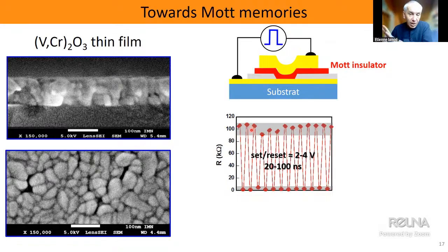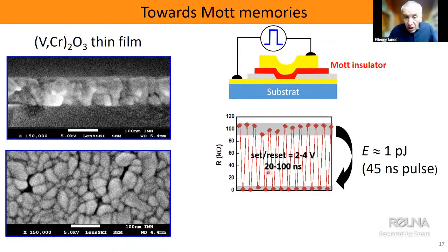What we believe is that this effect, what we call the reset transition, is not due to the same phenomena, but it's simply due to a Joule-heating effect that relaxes the system back to its initial state at equilibrium. And what you see in this example is the duration of the pulse that allows this transition in these really tiny objects, in which the typical size is a few hundred nanometers. In fact, the energy which is required to do this transition is quite low, typically around 1 picojoule.